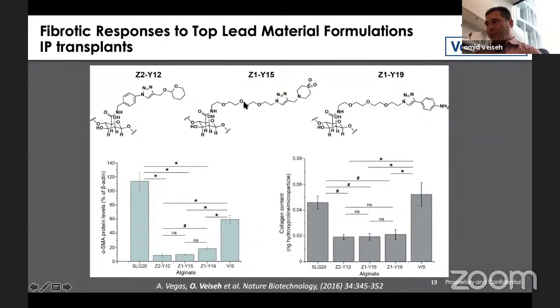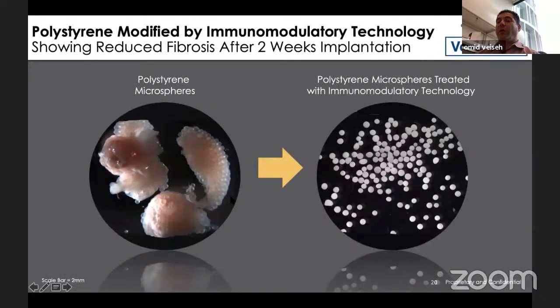And these are the formulations of the leads. You can see that they have a particular chemical composition, and what's common among all 3 of the leads is that they have this triazole group, and there's the PEG linker, this triazole group, and then there's what we call the cap. What's interesting is that these 3 performed much better than any of the other modifications we tested, and also allow us to reduce foreign body response and fibrosis of the alginates by more than 90%. And these were the ones that we wanted to move forward with further.